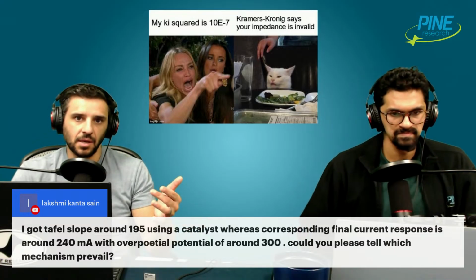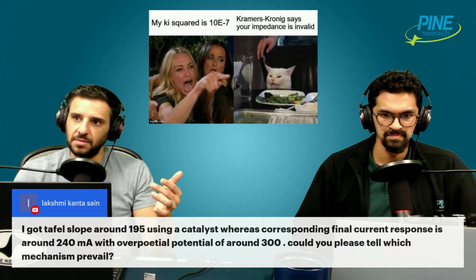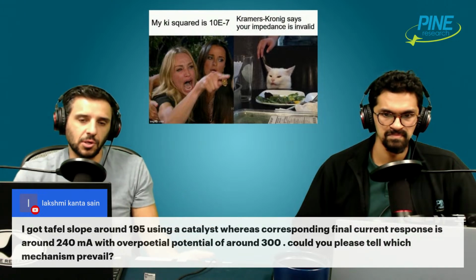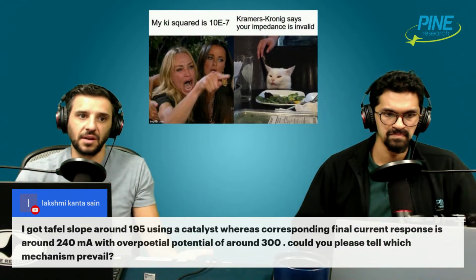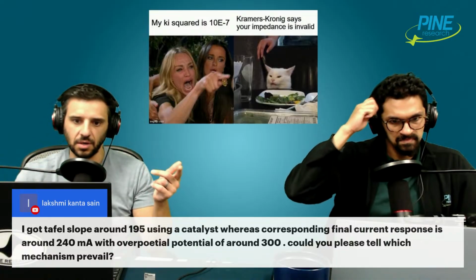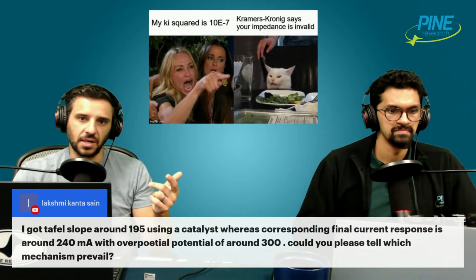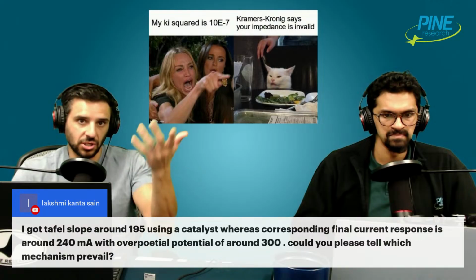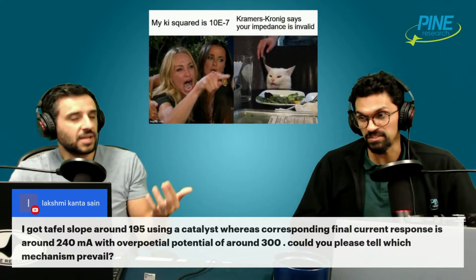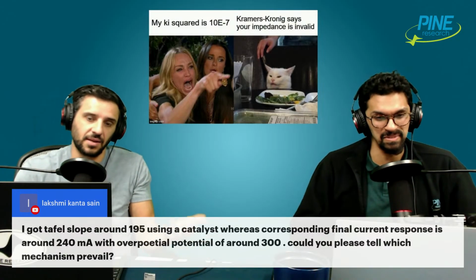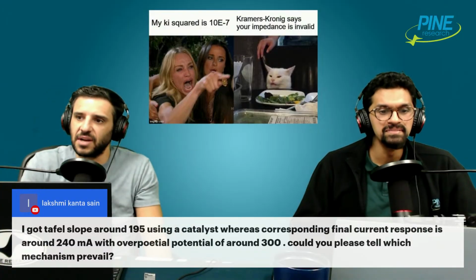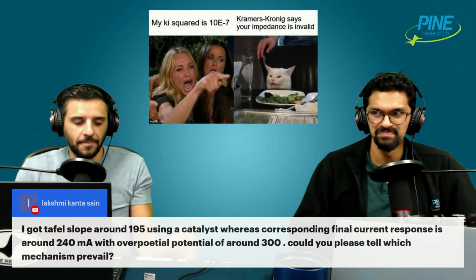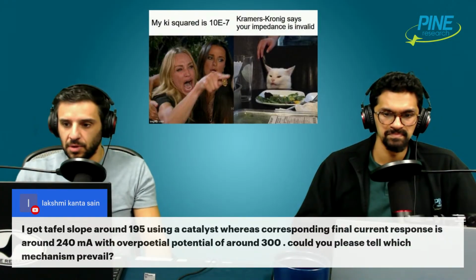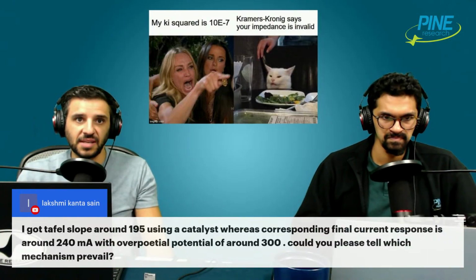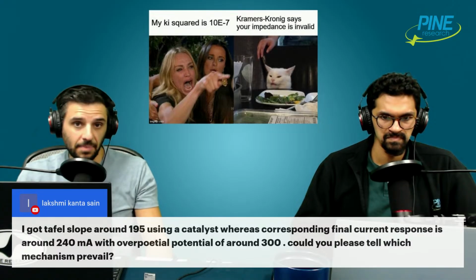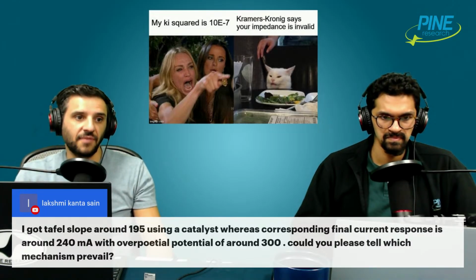So you might be discouraged, let's say, that your Tafel slope wasn't 120, because that would, in theory, mean one electron transfer kinetics, you know, what you would expect for HER. HER is a 2 electron process, so in theory you should be getting 60 millivolts per decade. Corrected myself on the fly there. Yeah, it's a 2 electron process. So it's higher. Does that say something about your kinetics? Maybe, or maybe it says that your Tafel plot is meaningless.